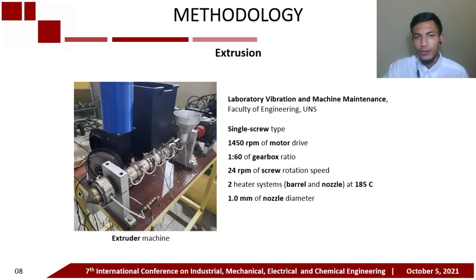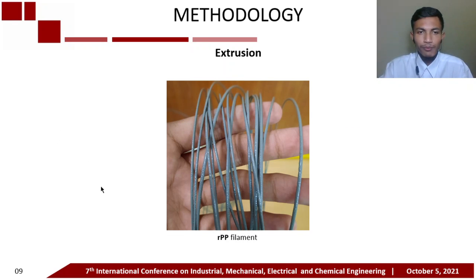The extrusion used an extruder machine owned by the Laboratory of Vibration and Machine Maintenance, Faculty of Engineering UNS. The machine is a single screw type and the rotational speed is 24 rpm. There are two heating systems applied to the barrel and nozzle. They are set at 185 Celsius. The nozzle diameter used is 1 mm. The extrusion process produces filaments, which are called recycled polypropylene or RPP filaments.